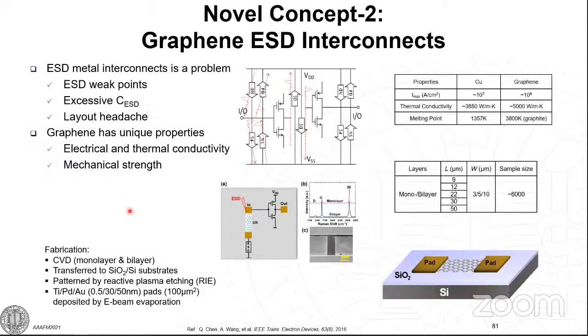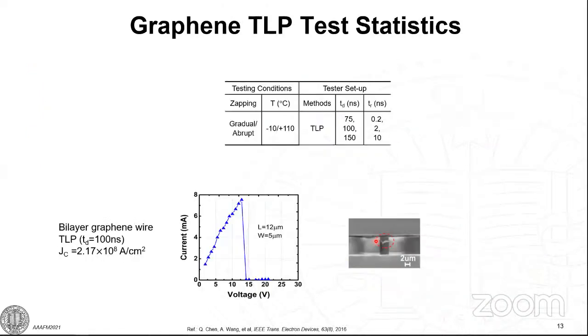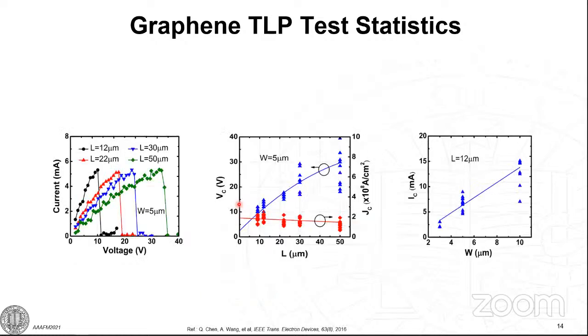Just quickly about another topic. Let's use the graphene ribbon for interconnect between the IC pad and any type of ESD protection structure. We did a lot of characterization and showed some very interesting results. First of all, IV measured by TLP showing the breakdown voltage and current over here. So this is the graphene current handling capability. And then we show the breakdown voltage and the current versus graphene ribbon length and width over here.